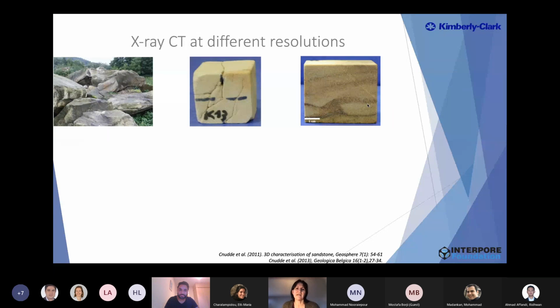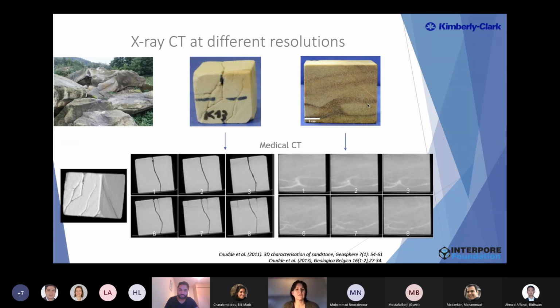But if you put these kinds of samples in a medical scanner, you will be able to clearly distinguish those fractures in 3D. You can follow how the fracture pattern is internally structured, and also see how the layers evolve, for instance in function of depth inside your sample. You see this because you have a contrast: the whiter, brighter areas have a higher average atomic number and are the iron-rich layers.